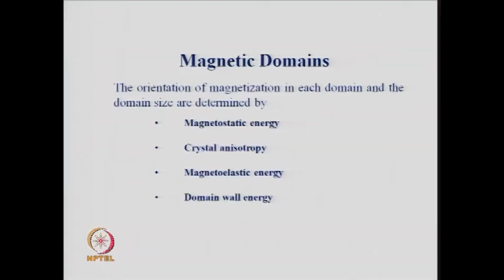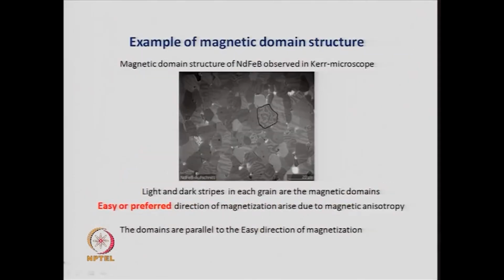Once you have information of the plane of polarization of the reflected light from different parts of the magnetic surface, then you can draw a map, and that map shows you the magnetic domains, exactly the plot you saw earlier in this picture, and similarly you can get the magneto optic Kerr effect from many other magnetic domains.